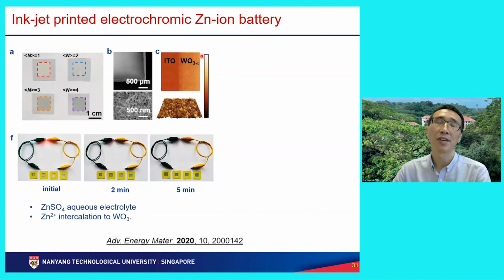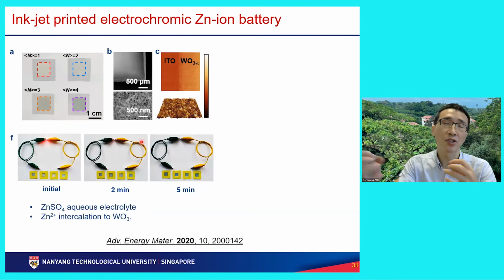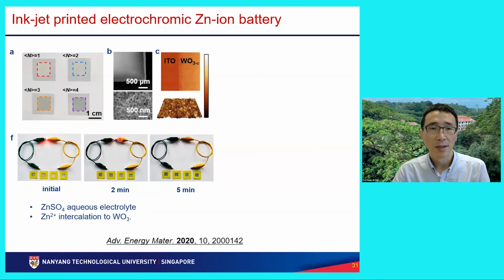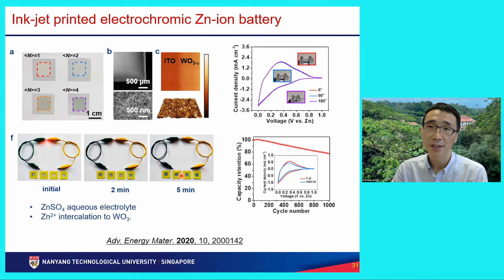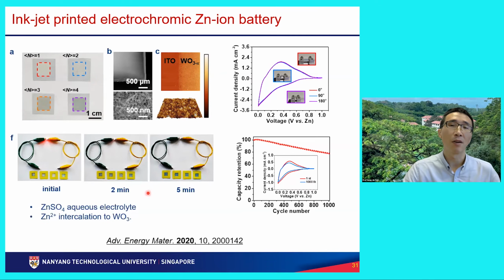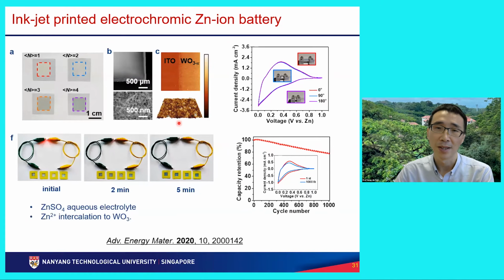Tungsten oxide is a very typical material for electrochromic devices. That means you apply potentials, and then the transmission becomes different. So if you make this a battery, when the battery charges and discharges, there are redox reactions. The zinc ion goes in and out of the tungsten oxide, making the tungsten oxide have different valence states, corresponding to different optical transmissions. So it can work first as a battery and also as an electrochromic device. If you make your car windows from these batteries, they can be self-powered smart windows.